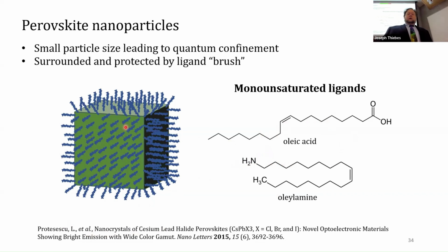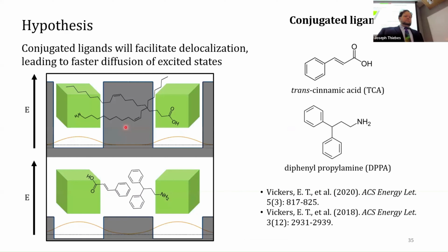So the functional groups attach to the polar surface of the perovskite, while the tails are hydrophobic. They protect against water and oxygen. However, they're also insulating, so they tend to inhibit energy transport. So it's hard to get transport of energy between nanocrystals. So we had this hypothesis after seeing some work by Vickers and coworkers. They were looking at photoconductivity using conjugated ligands instead of those aliphatic ones, and they found that there was some increased conductivity between nanocrystals.